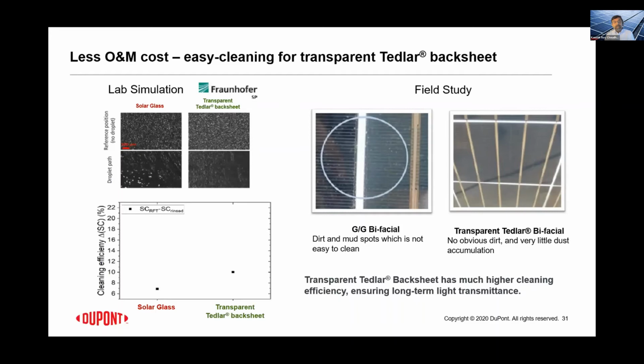But we have seen all indications that with the transparent Tedlar-based backsheet, there is much less obvious dirt accumulation. And once the dirt or dust does settle, it's much easier to clean with water because the surface of the Tedlar-based backsheet is actually a fluorinated material, which is naturally hydrophobic. So that is a good combination in this case. And this is important because it ensures long-term light transmittance stays at the level that we want, so that the power generation is not affected.